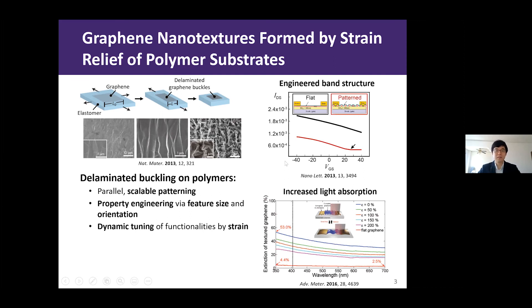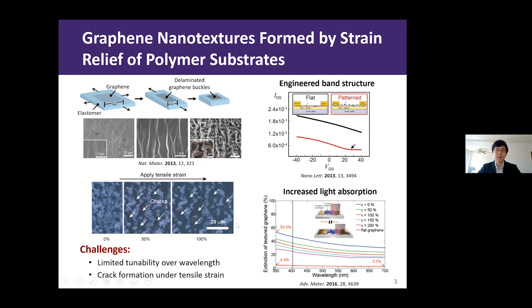What is unique about the delaminated buckles on top of this elastomer substrate is that you can tune the properties of graphene dynamically by simply stretching the underlying elastomer substrate. However, the delaminated graphene buckling has some limitations because it can only form globally uniform nanotextures over the entire surface. So if you want to tune the local properties of graphene, this process cannot address that need. Moreover, graphene typically cracks when we try to tune the textures by stretching the substrate beyond a few percent of strain.